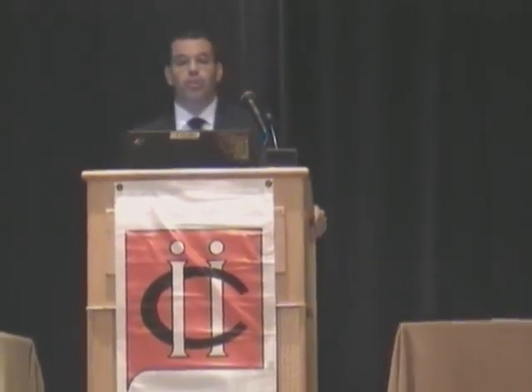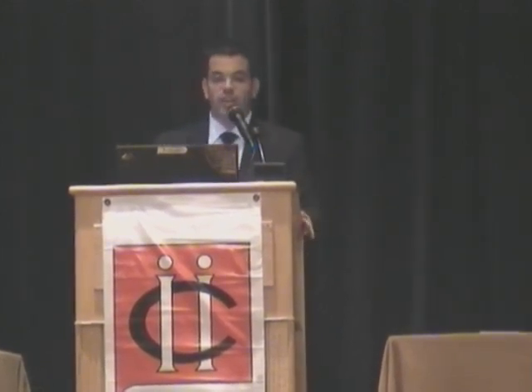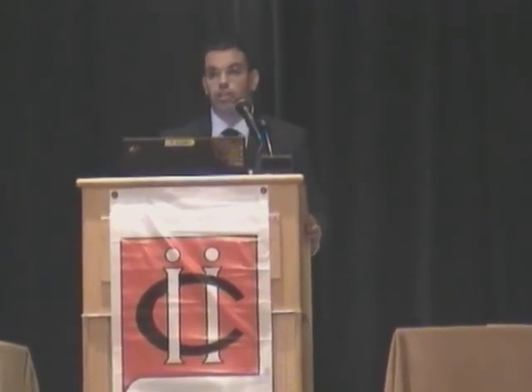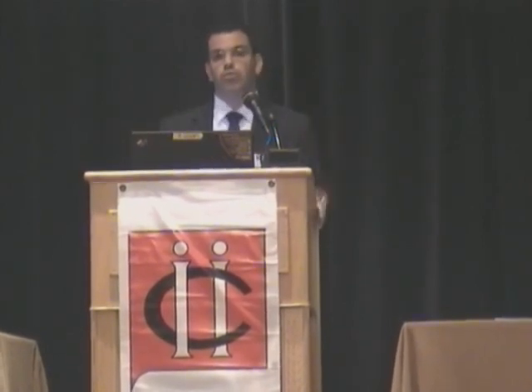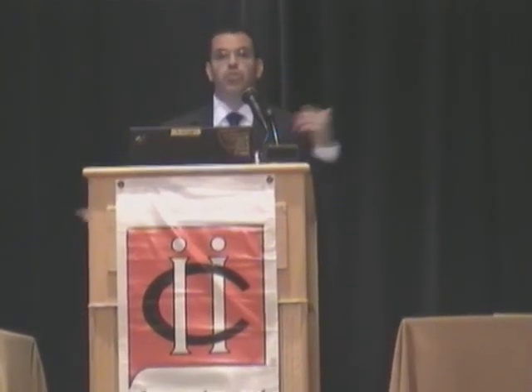Our observation mainly was that we've been using between 9 to 10 coats of slurry, and it created a long and ineffective shelling process. We experienced high scrap ratios due to shell cracking and inclusions. Our slurry formulation had no actual connection to the material we've been using. We actually found that the formulas that we had were 25 years old. The suppliers that we've been buying from for the past 10 years had changed. It's a different material, but the formulas kept on going.